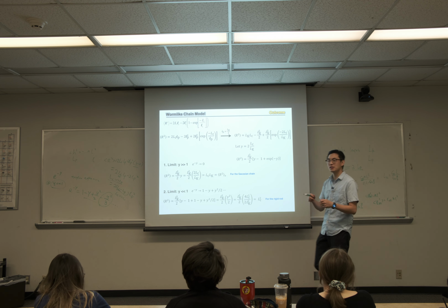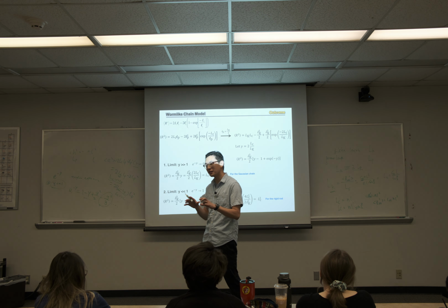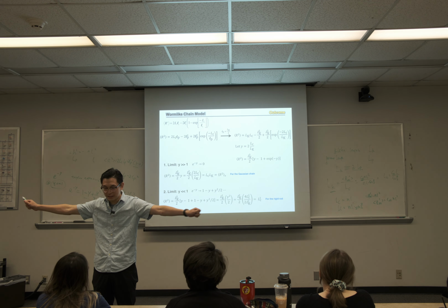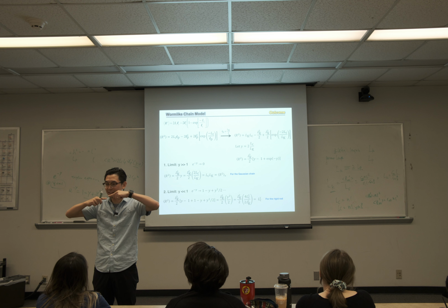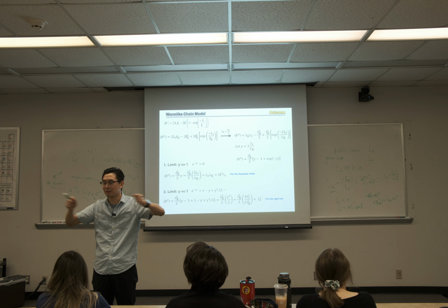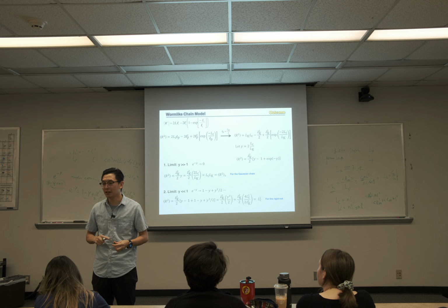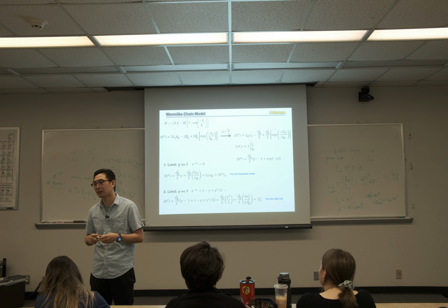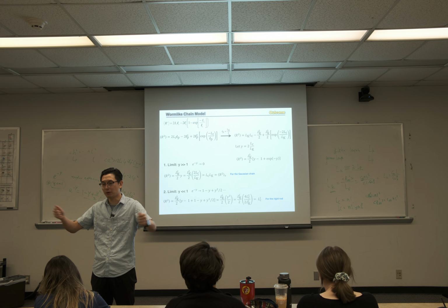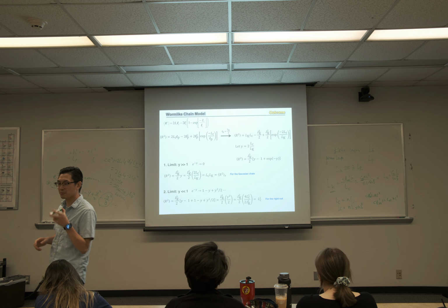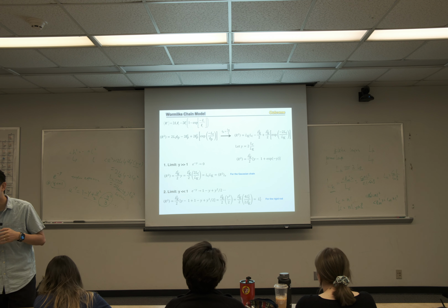If you have a freely jointed chain, when you're no longer constrained by the bond angle, you can pull it, then every bond can be lined up to be 180. So it will become that. But if you consider the freely rotating chain model, you have a bond angle you cannot break. When you pull it, it's going to be a zigzag shape. In that scenario, your contour length will be angle dependent.